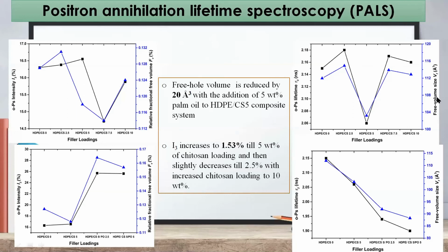So in molecular materials, we're looking at the lifetime of orthopositronium, which is environment dependent, and it delivers information pertaining to the size of the void in which it resides. So it can give you an idea about the free volume that the material occupies. The dependence of lifetime and free volume on the composites is shown on the right hand side, and it is mainly associated with the size of the free volume in the polymer composite. Generally, as the filler concentration increases, the concentration of the free volume should decrease.